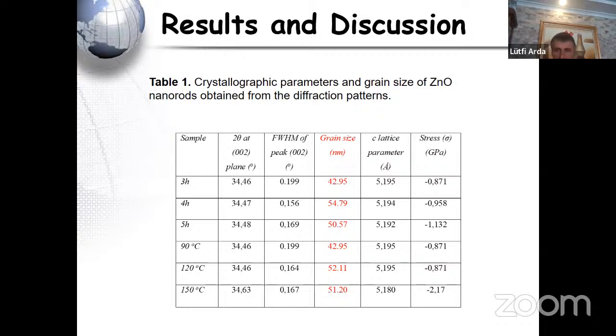Also, the last column is the calculated stress values, and look at the sign. All of them are negative. That negative sign indicates that the stress on the C axis is compressive. The compressive stress increased from minus 0.871 to minus 1.132 gigapascal as the growth time increased from 3 hours to 5 hours. Although little change was observed in the stress value of the zinc oxide nanorod for the temperatures 90 and 120 degrees, when the growth temperature reached 150 degrees, it was found to be minus 2.17.